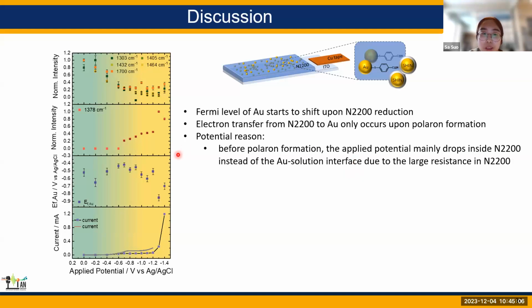So for discussion, what we observe from this Stark shift measurement is that the Fermi level of gold will shift upon N2200 reduction or upon polaron formation. And it indicates to me that the electron starts to transfer from N2200 to gold only upon polaron formation. And I think the potential reason behind that could be that before the polaron formation, the N2200 will have a large resistance. So the applied potential will mainly drop inside N2200 or at the N2200-gold interface instead of at the gold-solution interface.